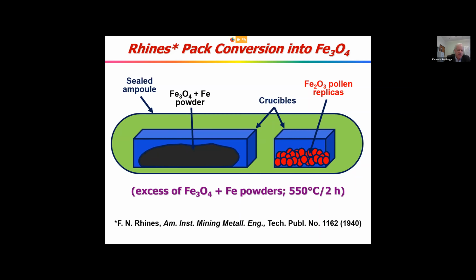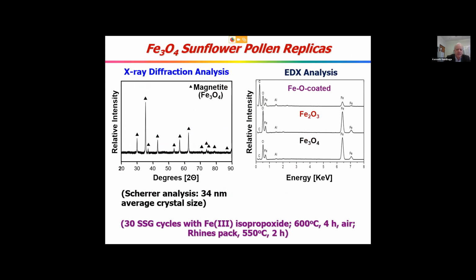The excess magnetite and iron establishes an oxygen partial pressure that will allow for only the formation of magnetite from hematite. And so that's what we did. And so we generated a magnetite pollen replica. As you can see from the X-ray diffraction, you can see it from the EDX iron.